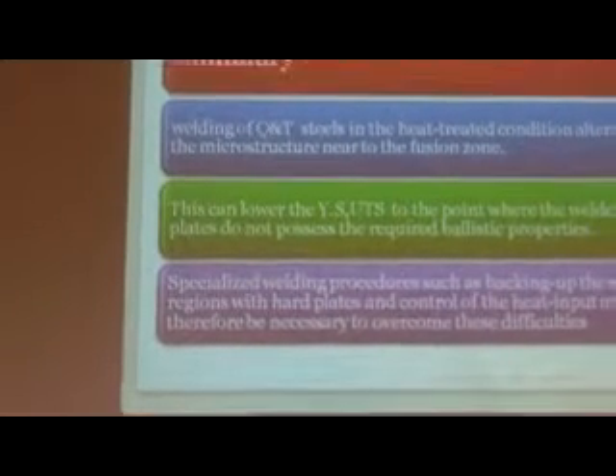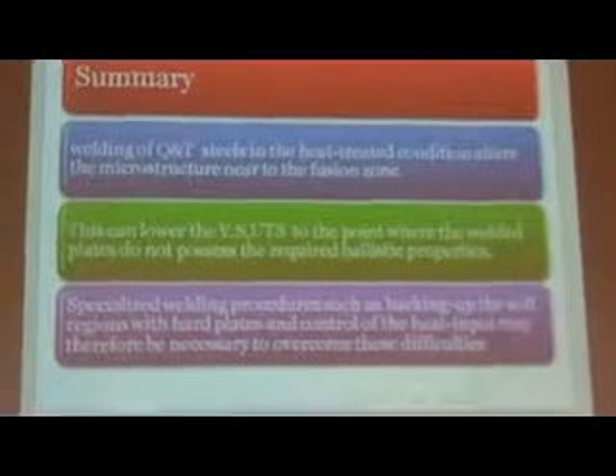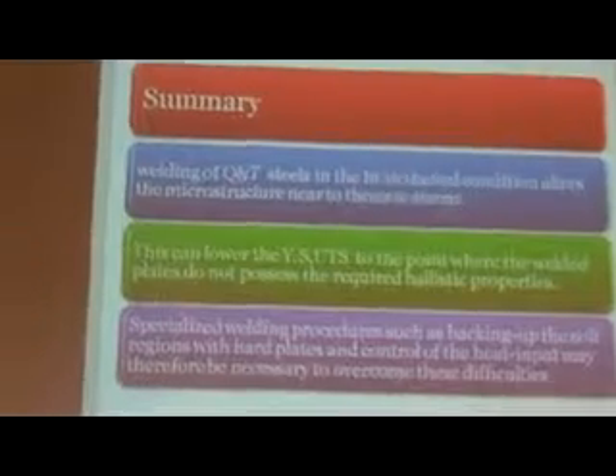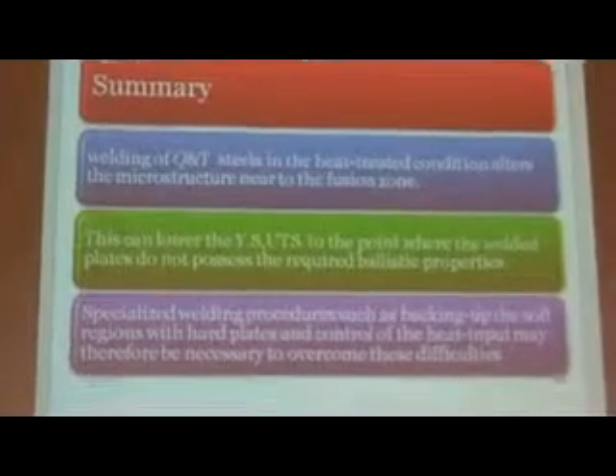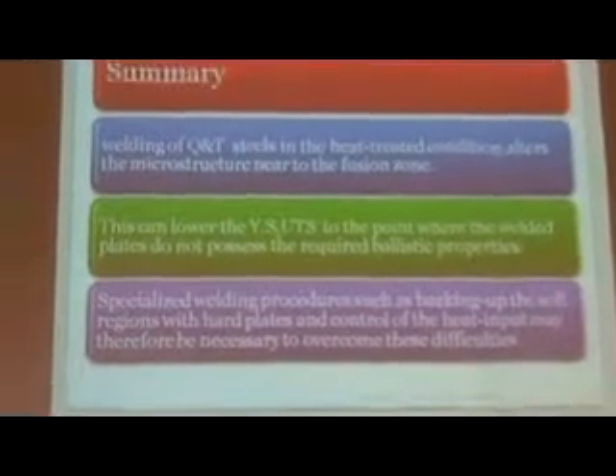Summary: welding of Q&T (quench and tempered) steel in a heat treated condition definitely alters the microstructure near the fusion zone. This is unavoidable. And this microstructural alteration definitely lowers the yield strength and, in parallel, the ultimate tensile strength, to the point where the welded plates do not possess the required ballistic resistance properties. Specialized welding procedures, such as backing up the soft region with hard plates or control of heat input, are therefore necessary methods to overcome this kind of difficulty.